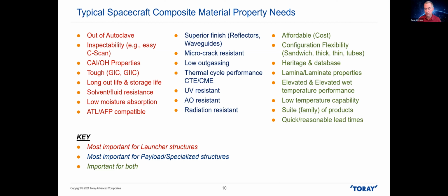When materials, especially composites, thermal cycle, there's a tendency that you have to fight that will cause the matrix to generate small cracks. And these can run through the thickness. These can run along the ply interfaces. They may not be catastrophic on their own, but what will happen is there's a relaxation. So effectively, you will end up with a lower stiffness structure when you have micro cracks present. And to the extent you have more and more micro cracks, it would become more and more relaxed.